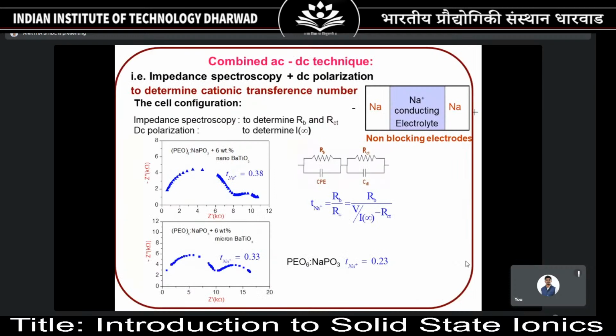This is a technique, that's what I was showing. There is Wagner's polarization, which will just polarize and check the initial current and final current, and you say whether it is ionic conducting or electronic conducting. Here there is a technique called the combined AC-DC technique, where you use a sodium ion conducting material. I am working on sodium ion material, so I am using here a sodium ion conducting material sandwiched between 2 sodium blocks. We call this configuration a non-blocking electrode configuration, and you run impedance spectra.